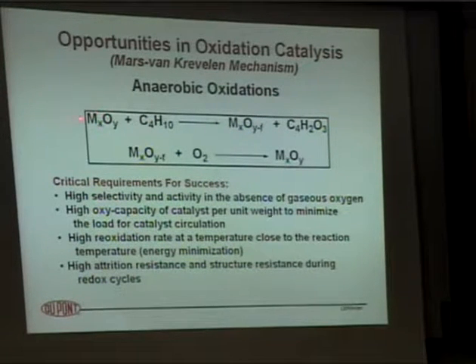The oxygen that comes out causes the catalyst to be reduced. That reduced catalyst then is moved to a separate zone, reacted with air or oxygen to regenerate the more oxidized species, which then goes back over into the other reactor and goes round and round and round the loop. So you're using the lattice oxygen as a source of the oxygen to make the maleic anhydride. And the advantage there, of course, is you're eliminating a lot of radical reactions because the gas phase oxygen or air is separate from the hydrocarbon.